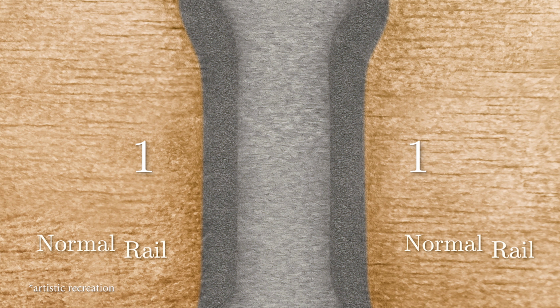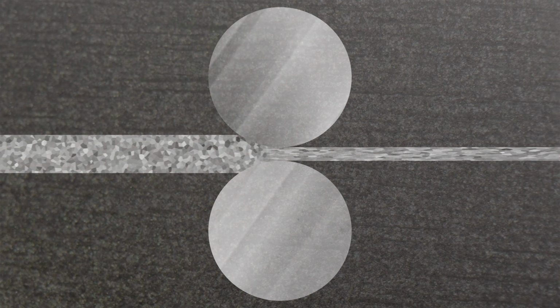In the weld, you can see 3 different zones. The normal rail is on either side with a horizontal grain due to how it was rolled in the steel mill. In the middle is the thermite steel. You can still see a bit of horizontal grain, but here it doesn't come from the steel being rolled, since this just solidified from liquid. Instead, it formed from the solidification front moving from the sides to the center, and when the crystals from both sides meet, it creates tiny microscopic pores, resulting in this darker line in the center.